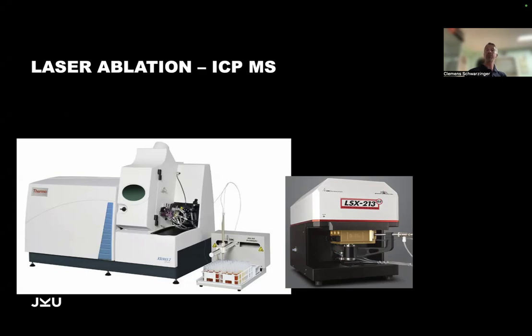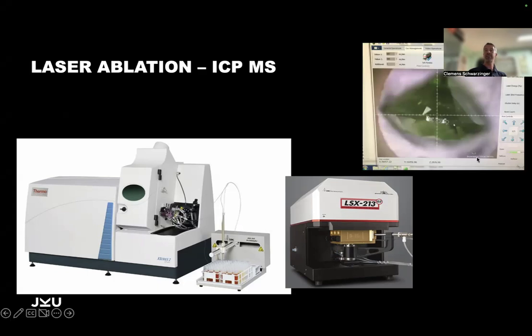That means we put our gemstones in a small chamber and we shoot at it with a laser. I think there's a nice slide here. There's a demantoid garnet, and you see here on the girdle 3 small circles. We use something like a diameter of 50 microns, and we shoot real holes into our gemstones. But the holes are very tiny, they're shallow, like 1 to 2 microns in thickness, and you wouldn't see them if you're not looking at them with a microscope or a loupe. And if they disturb you, you just repolish them without any loss of weight, typically in the thousands, 0.001 carats range. So with these 3 small holes, we get 3 times the complete chemical analysis of our gemstones.